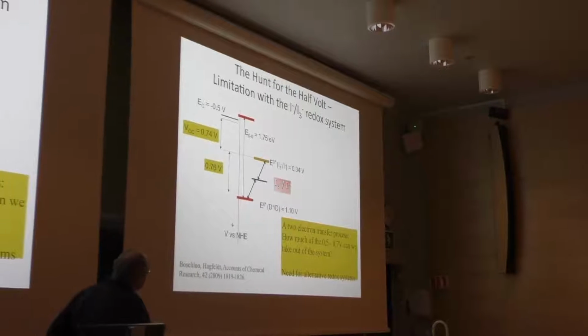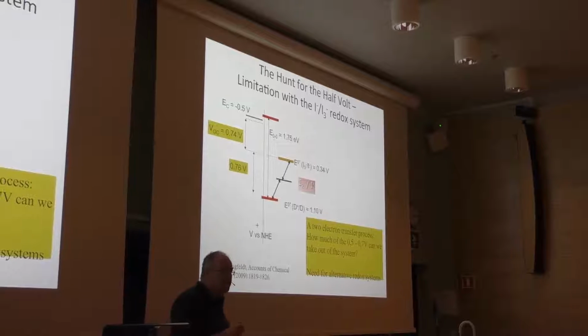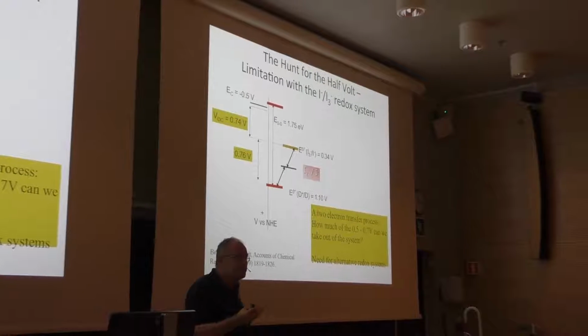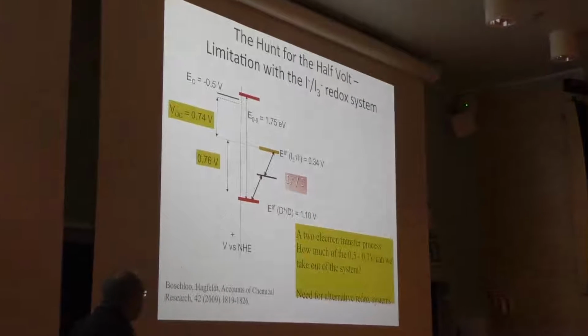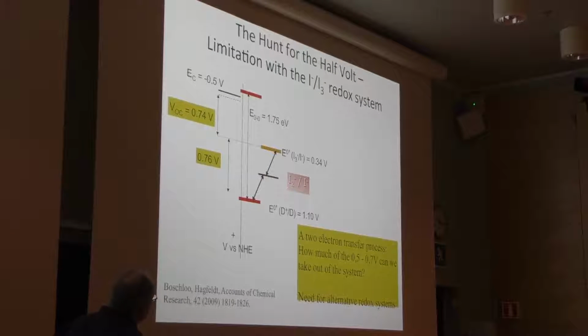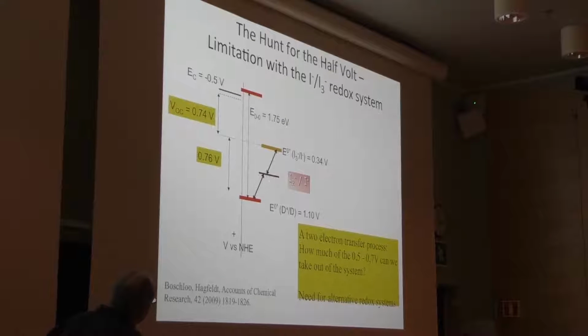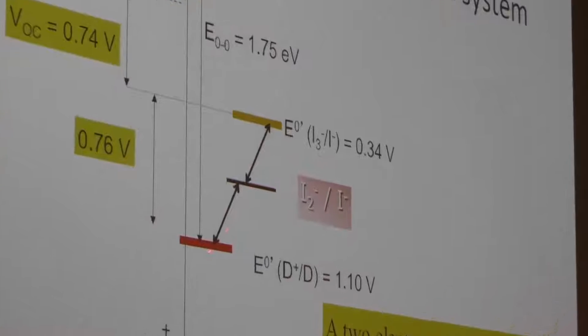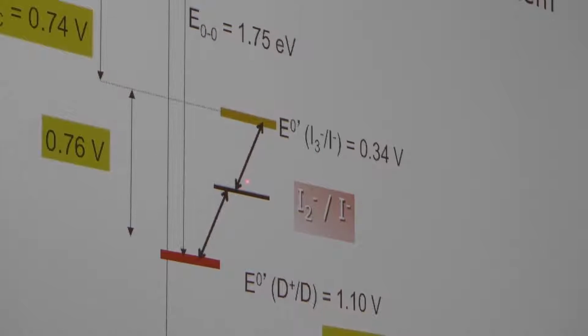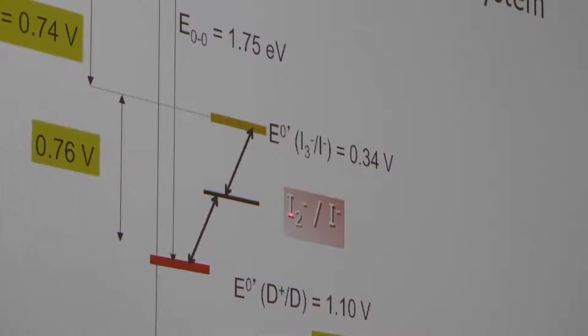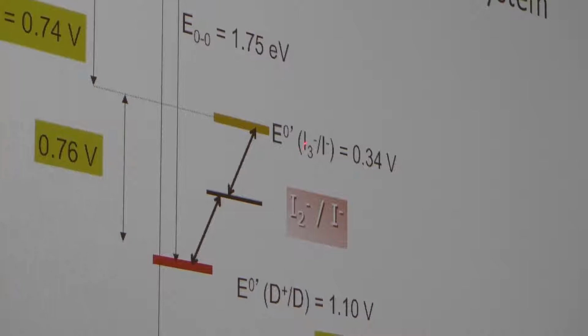So iodide, triiodide is not a simple redox system. It's a 2-electron process. It goes through intermediates. And the intermediate of importance we identified here is this iodine radical. So really the driving force to regenerate the dye is from this redox system, iodide, iodine radical. And the difference here was not easy to measure, but we think it's around 0.3, 0.4 volts. The rest of this 0.7 is just to let iodine radical react with an iodide to form the I3 minus. So this is the problem with the iodide system.